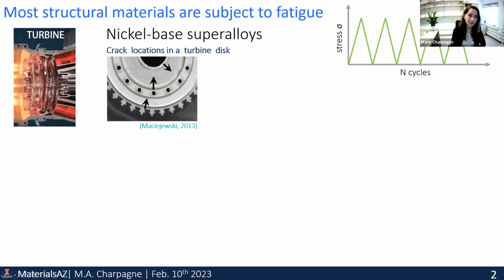But when we extract one of those turbine disks in the hottest section and look at where the fatigue cracks actually developed, we find that they are not even located in the region of the disk that was exposed to the highest temperature, but rather towards the edge where you have lower temperatures, or relatively lower. So we find that temperature is not the only problem. The most detrimental areas are actually in the cooler sections of these turbine discs. That tells us where to look and where fatigue really is critical.